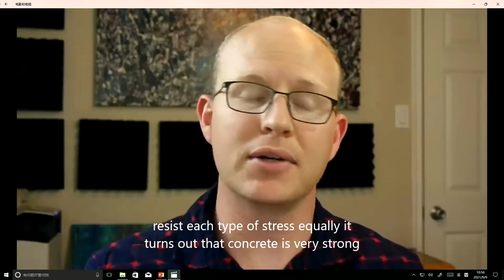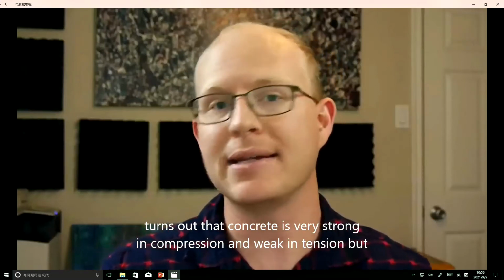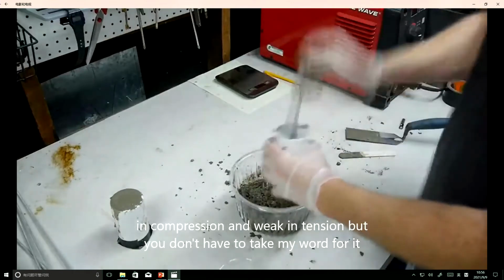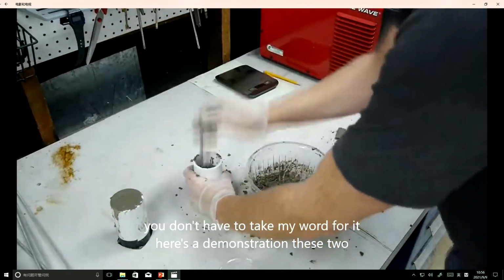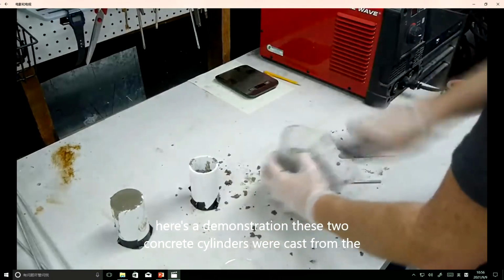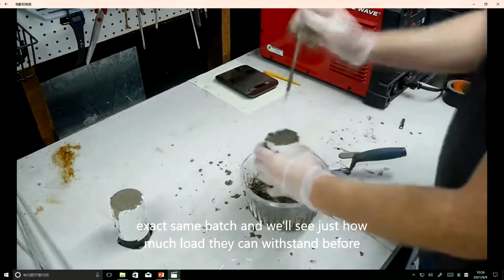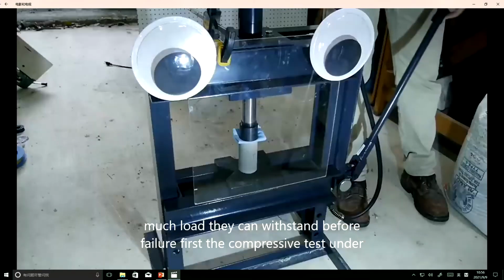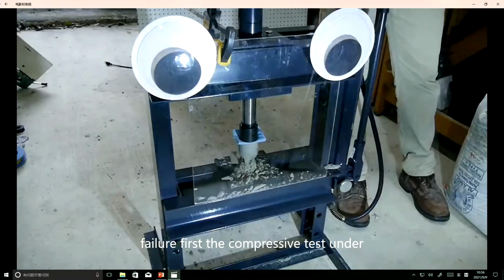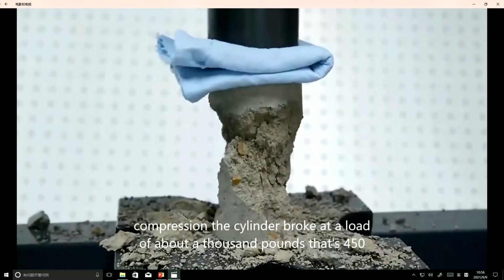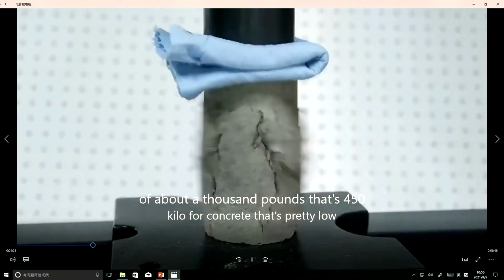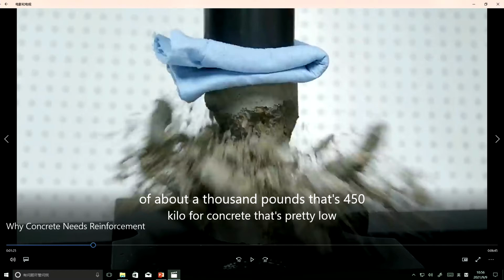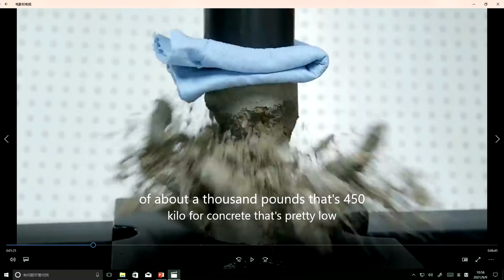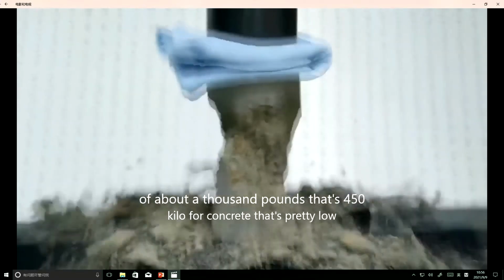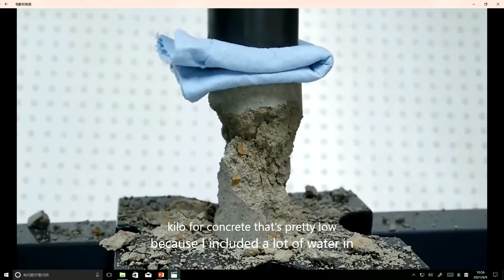It turns out that concrete is very strong in compression and weak in tension. But you don't have to take my word for it. Here's a demonstration. These two concrete cylinders were cast from the exact same batch, and we'll see just how much load they can withstand before failure. First, the compressive test. Under compression, the cylinder broke at a load of about 1,000 pounds. That's 450 kilos. Remember this value, 450, that's pretty low for concrete, because I included a lot of water in the mix.